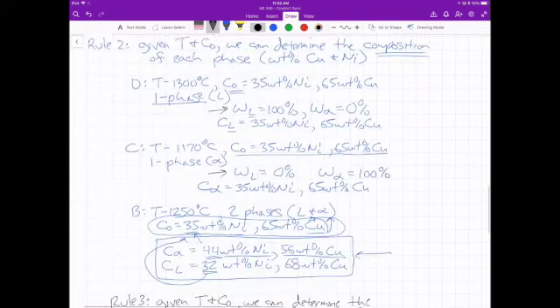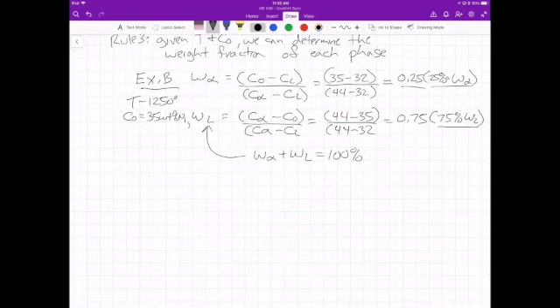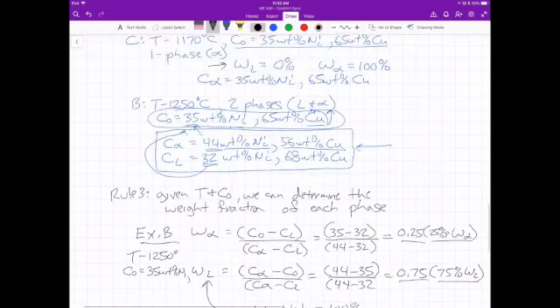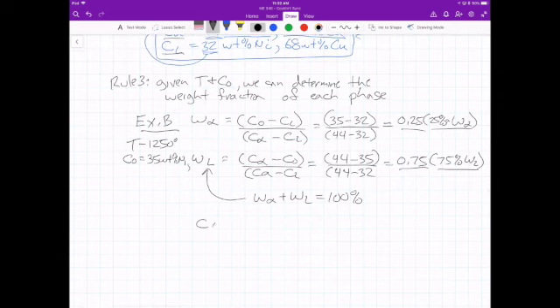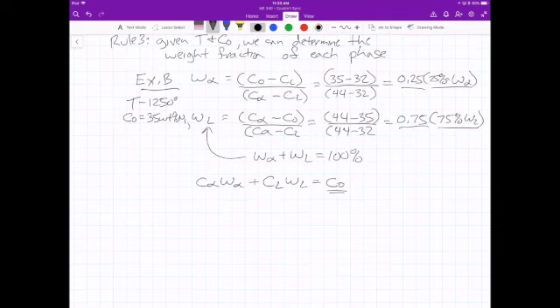And that's what the weight fraction tells us. Okay, then again, like I said, if you have these weight fractions and you have the compositions in each phase, if you multiply those together, you get a weighted average, which will give you your original concentration again. So if I take the concentration of the solid, multiply that by the weight fraction of the solid, plus the concentration of the liquid times the weight fraction of the liquid, I will get my C naught. Because C naught never changes, unless I melt the material and add more of another component, which is not really practical. So this always has to stay the same. It's just that we're moving copper and nickel into different phases at different locations. Okay, so if I put in my numbers, C alpha was 44 weight percent nickel. The weight fraction of alpha was 25.